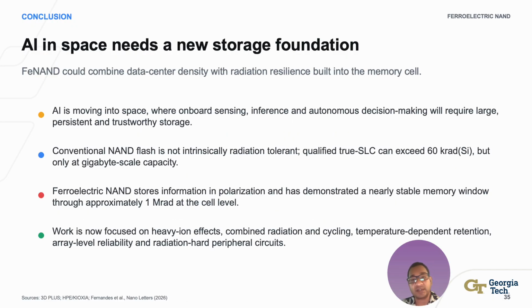I'll close with 4 points. First, AI is moving into space, and onboard sensing, inference, and autonomy require persistent, trustworthy storage in space. Second, conventional NAND is not intrinsically radiation tolerant. Qualified true single-level cell products can exceed 60 kilorads of TID, but their capacity is measured in gigabytes per package, not in terabytes. Third, ferroelectric NAND replaces trapped electronic charge with switchable polarization, and our cell-level memory window remains nearly stable to approximately 1 megarad.